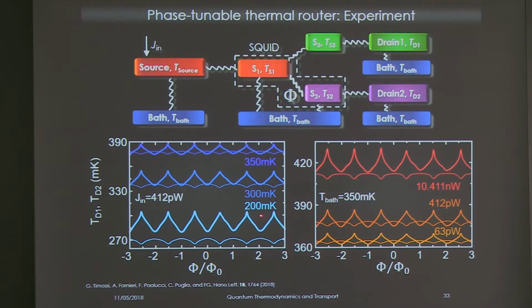Then, by increasing the temperature of the lattice, we increase the electron-phonon coupling, and the two temperatures start to cross, and then there is a swapping regime where the temperature of one is larger than the other. This mechanism can be implemented as well by fixing the bath temperature and changing the amount of power injected here. For instance, we go from low power, where there is already a regime where they can swap, up to a larger heat current, where they are completely separated. This can be explained with all the relaxation occurring inside.